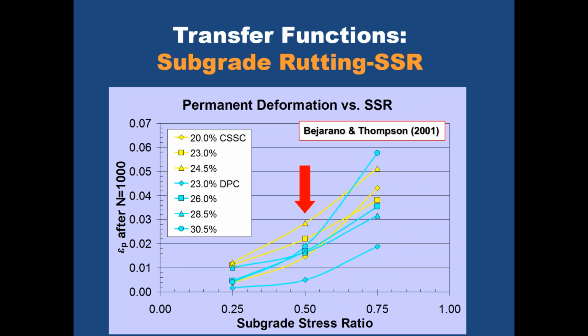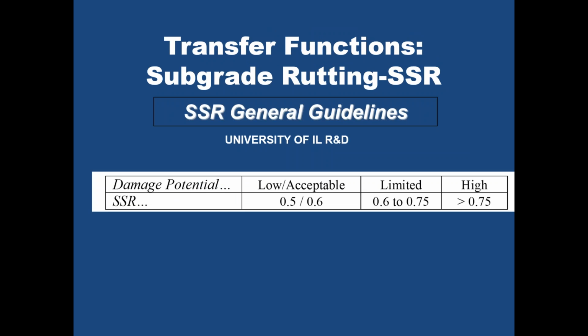This is another one, different soil. And the same sort of thing shows up if you have increased stress states, regardless of the moisture content, you still have increased permanent deformation. So subgrade stress ratio is valid. We find it works very well. These are some early ideas. Franco Gomez and I proposed these for a meeting in Portugal with ISAP many years ago. And you can see for SSR values 0.5, 0.6, you're going to last a long time. You move up to 0.75 or so, you'll have a more limited life.